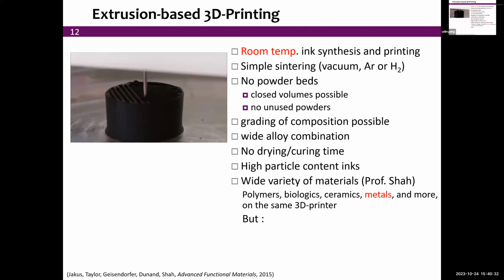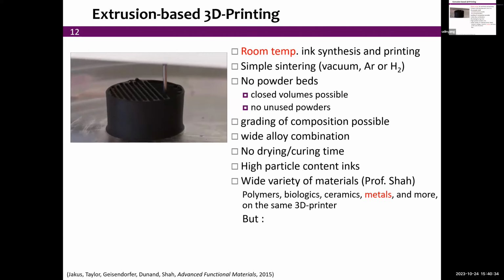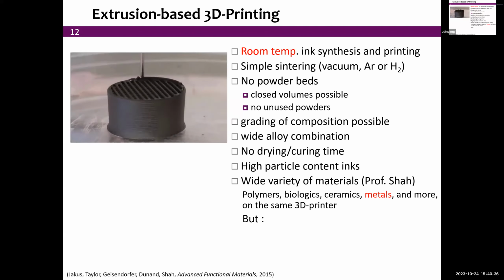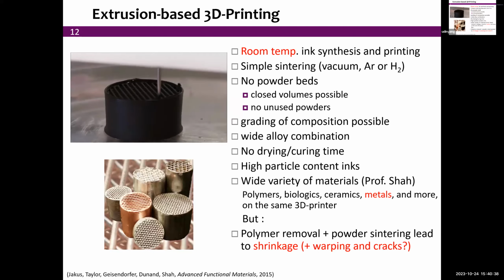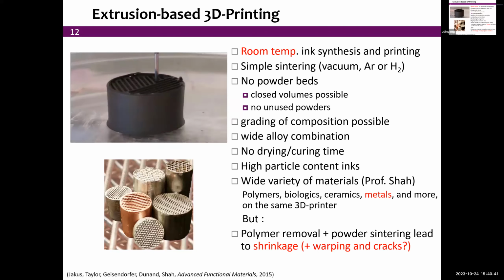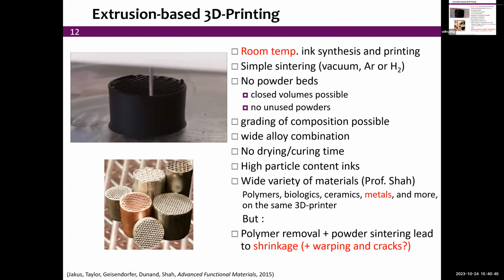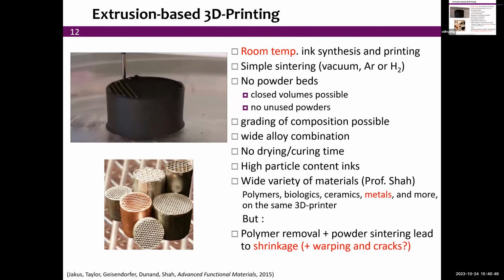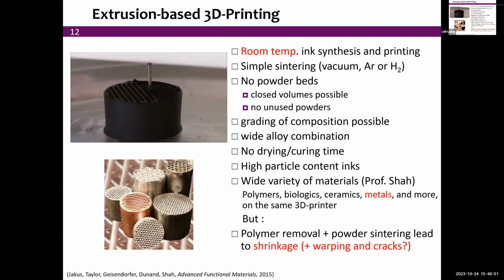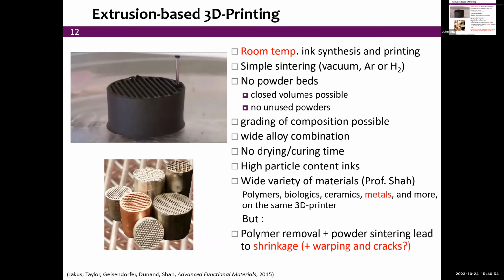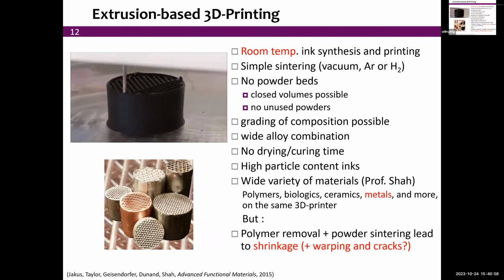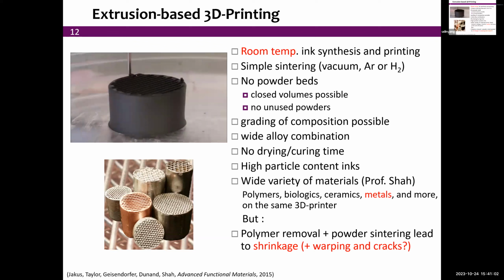And Professor Shah, my colleague, is also not just doing metals, but she's also doing polymers, biological materials, ceramics, and others. But we have now to deal with the removal of the polymer and the subsequent sintering of the powders, which leads to shrinkage, which is okay and unavoidable, and hopefully no warping or cracking. Because after all, one of the reasons we do this is to avoid the cracking that happens in other melting-based additive manufacturing, where the thermal gradients are really often cracking the material.